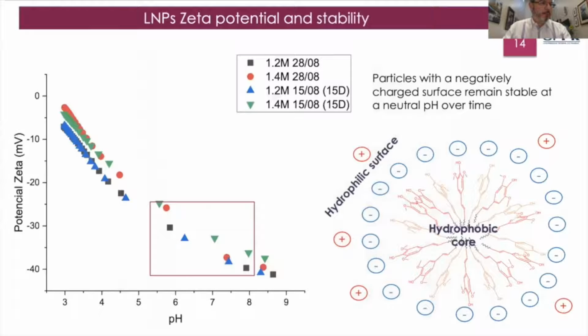The zeta potential was an important measurement in our studies, because by doing so, we were able to demonstrate that the particles were negatively charged at the surface. And that surface remained stable at neutral pH over time. And one sees that the zeta potential at pHs close to neutral and above were around minus 40 millivolts. That is telling us that those lignins, especially in that range of pH, could be considered relatively stable for several probable applications in suspension.